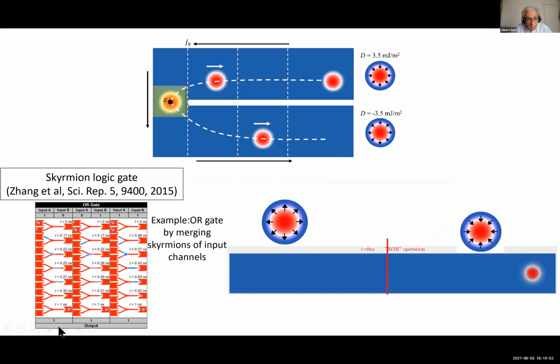For example, this logic gate has been proposed to use skyrmions of different chirality, and the mechanism of the gate is the merging or annihilating of skyrmions of different chirality. And if one wants to be speculative, there is certainly the possibility, with this type of skyrmion, to have tracks with different types of skyrmions of different chiralities, and annihilation of skyrmions by collision between skyrmions of these two types.